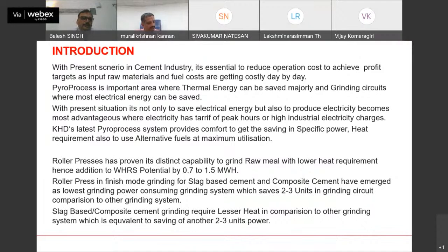So in today's scenario, if we see one best optimized or well advanced plant, the total pyro process electrical consumption can be 42 kilowatt per ton of clinker, and at the same time it can generate 35 to 36 kilowatt per ton of clinker in net. That means only 7 to 8 kilowatt has to be used to run this plant. But it is my belief that in the coming time, this also will be optimized, and the day will come when we say, okay, this is the pyro plant which is operating without taking any electrical units.